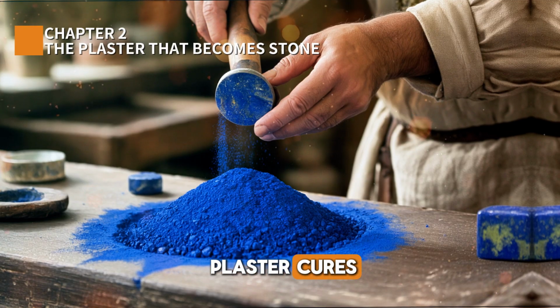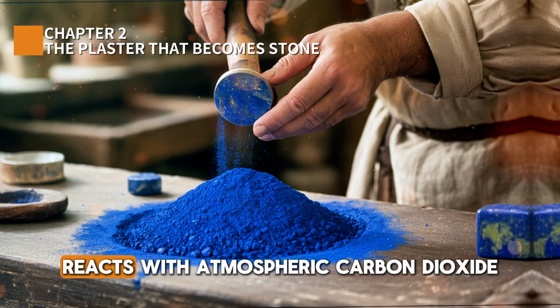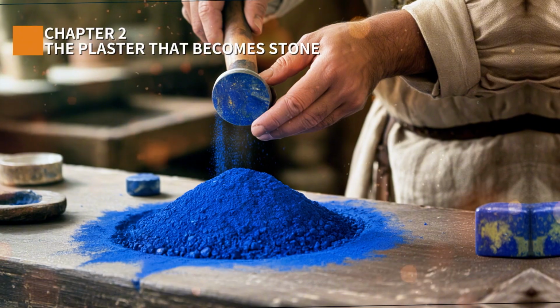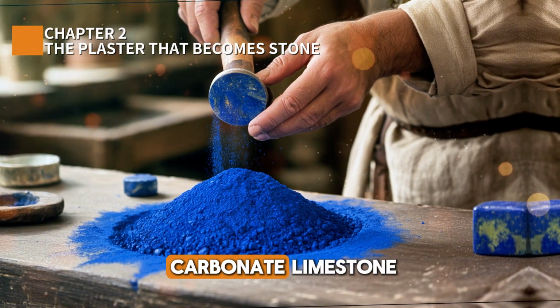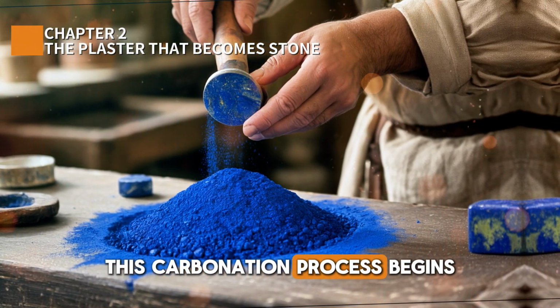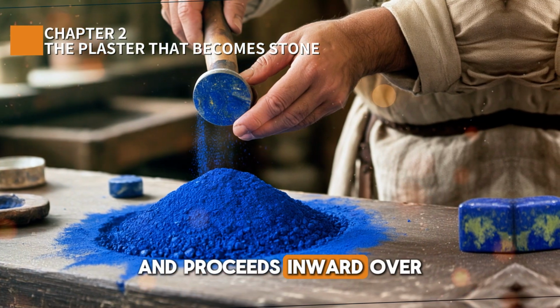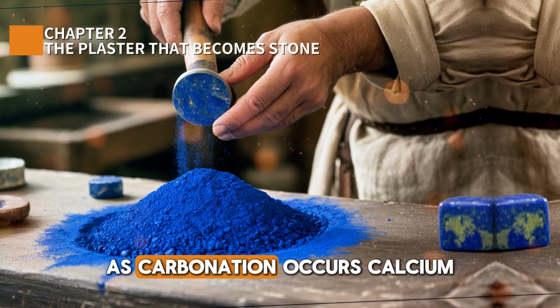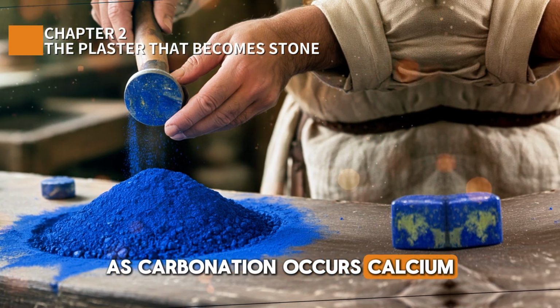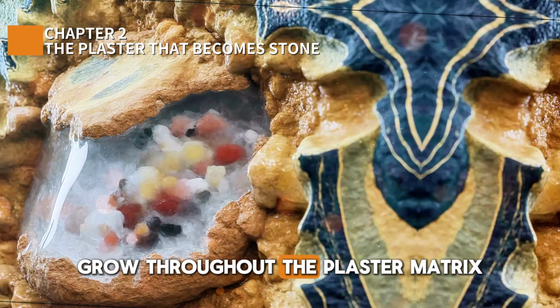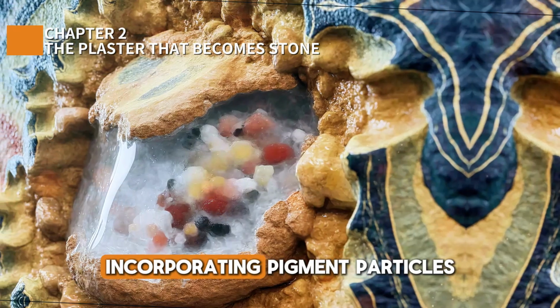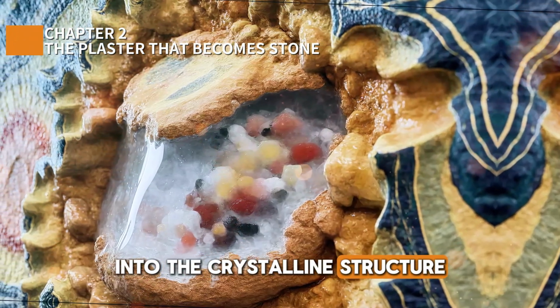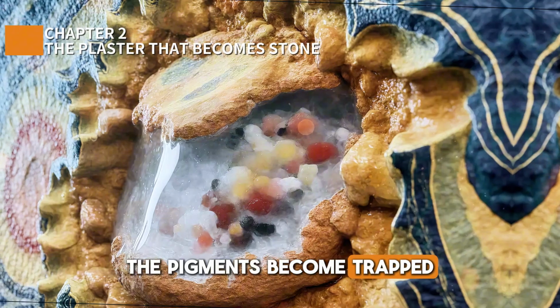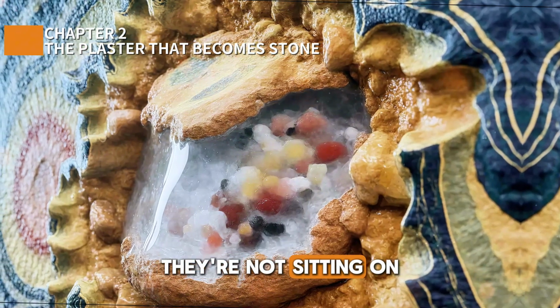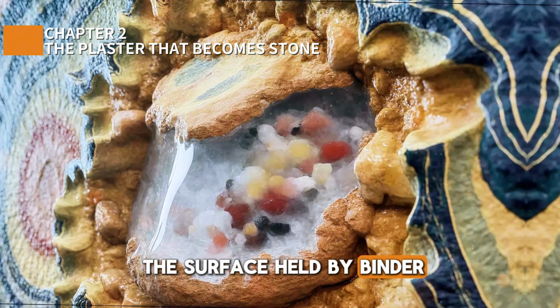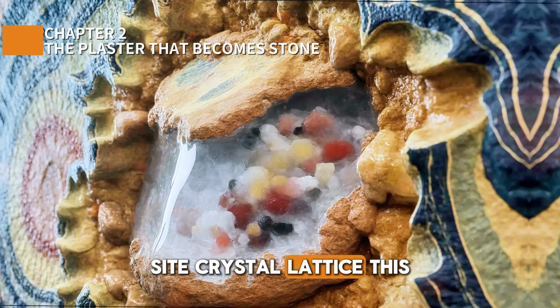As the plaster cures, calcium hydroxide reacts with atmospheric carbon dioxide, slowly converting to calcium carbonate limestone. This carbonation process begins at the surface and proceeds inward over months and years. As carbonation occurs, calcium carbonate crystals grow throughout the plaster matrix, incorporating pigment particles into the crystalline structure. The pigments become trapped in stone, literally. They're not sitting on the surface held by binder, they're embedded in calcite crystal lattice.